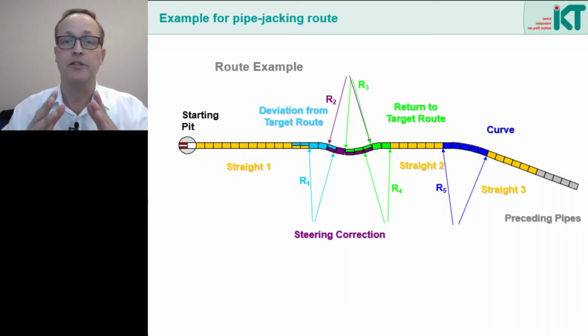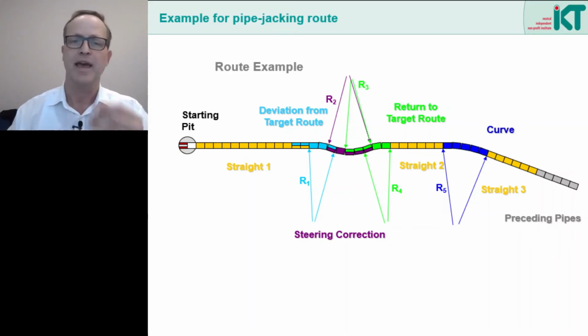The pipes come out of a starting pit on the left and they then pass through the route in several geometric situations. First of all, there is a straight line. The pipes are pushed in one after the other and therefore they experience a centric cyclic load according to the number of pipes. Even with the straight line, however, there are always deviations from the target route. This is the reason why the tunneling machine must be steerable. By steering the shield, the deviation is compensated, followed by the return to the target route. Afterwards, the pipe route continues straight on.